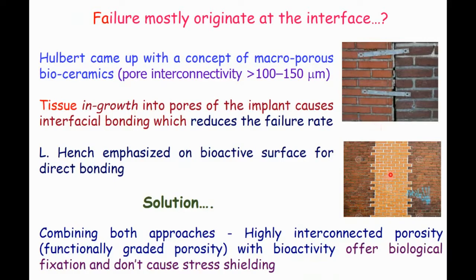Similarly, if we have new walls which can cross-talk with the old wall, then only you can have a nice bonding, stitching, right? In this context, Hulbert, a scientist from a US university, proposed that if you can use absolutely inert ceramics and make them macroporous, with porosity of 100 to 150 micron, then we can avoid the interfacial failure between the implants and the tissues.